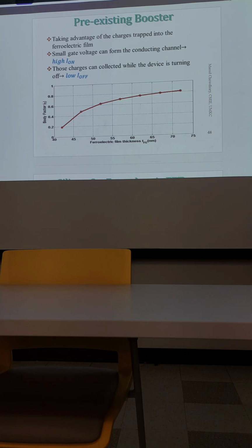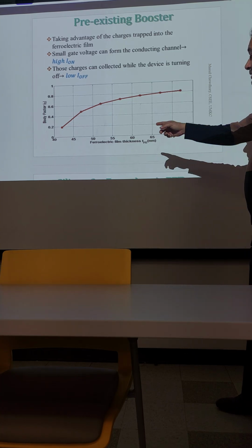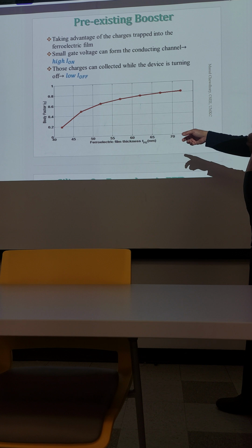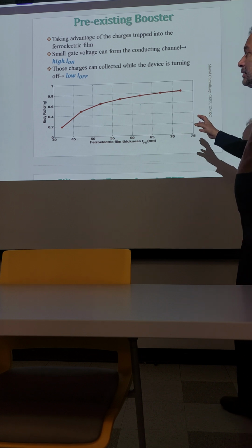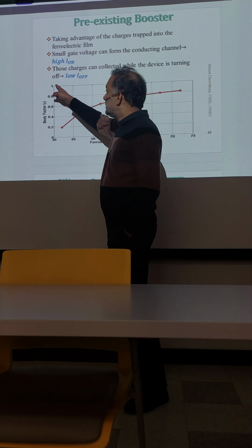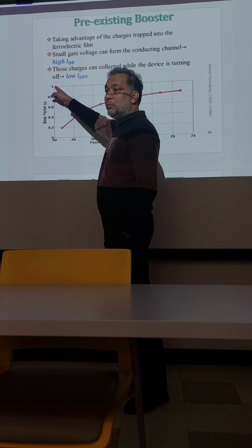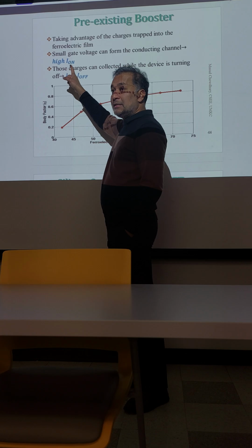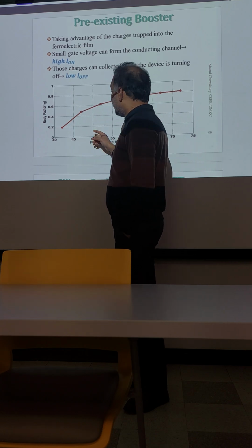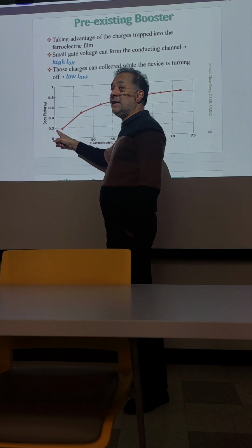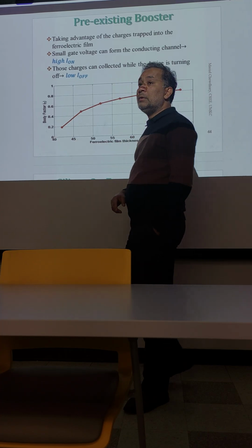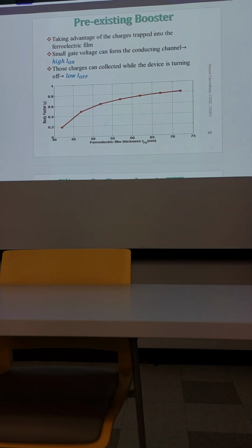We changed the thickness of that ferroelectric film and other parameters, and then the body factor, we know that practically it is greater than 1, but we played with the thickness and were able to theoretically achieve up to 0.2 body factor, so then overall subthreshold swing will be 60 times 0.2 theoretically.